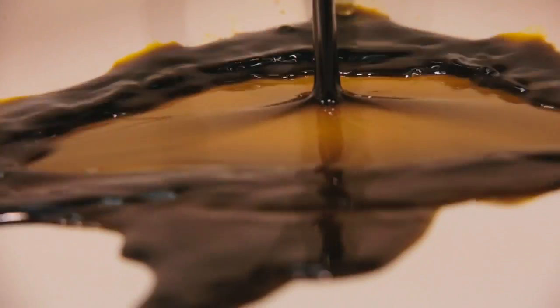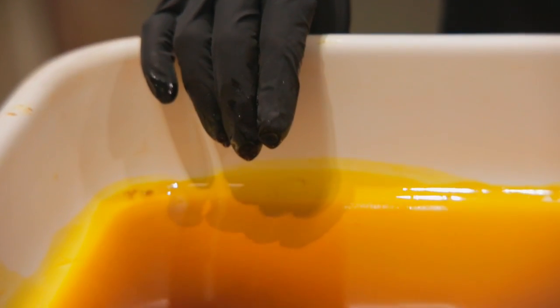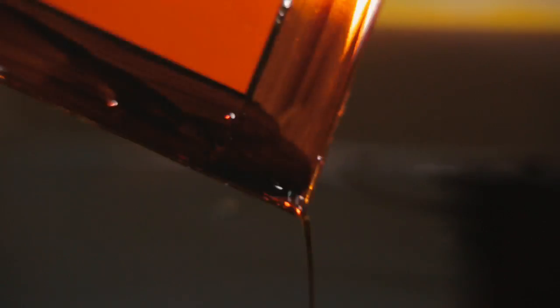Then we etch the plate in a series of 3 to 4 baths of ferric chloride with specific gravity amounts of water added to increase the amount of water which will penetrate the thicker amounts of gelatin that are in the image. So it's really starting to etch now.